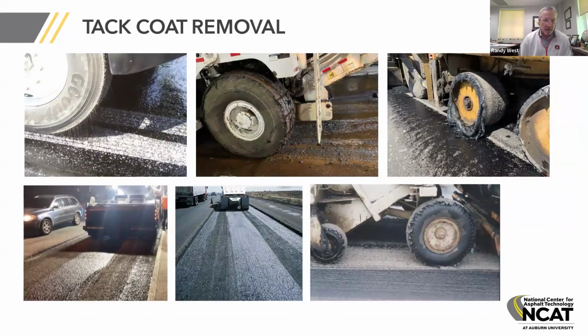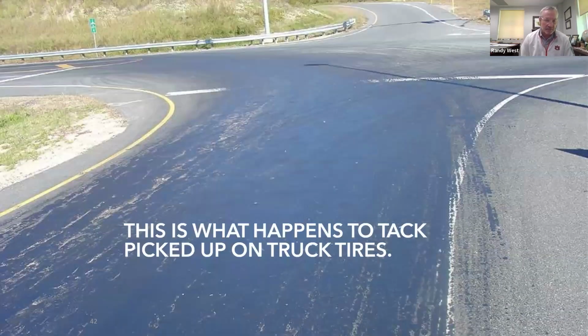Another issue that we don't talk about very much is tack coat removal, and the reality is a lot of tack gets picked up by the construction equipment, by the trucks, by the MTV, by the paver. And so the most critical area of the pavement that needs a good bond, which is the wheel paths, is probably where we have, in a lot of cases, no tack. And this is what happens to the tack that gets picked up on those haul trucks. It gets deposited somewhere else, and that's not good aesthetically or on a safety aspect. That's not going to be a good place to be slamming on your brakes.